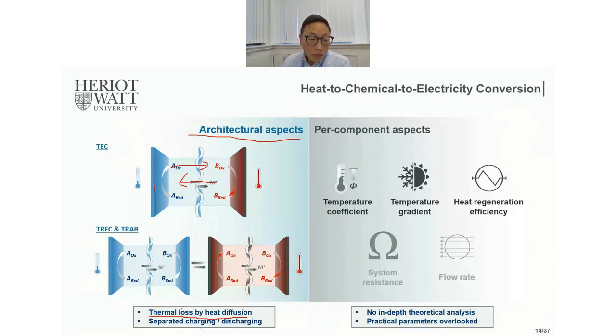And also TREC and the TRAB system, even they charge at the low temperature and discharge at the high temperature. But unfortunately, between these two transitions, we also can have a huge loss in between, heat loss in between. And the most important thing is, unfortunately, we can only do charging or discharging one by one, not at the same time. That is the quite big disadvantage of this kind of electrochemical heat to electricity conversion system.